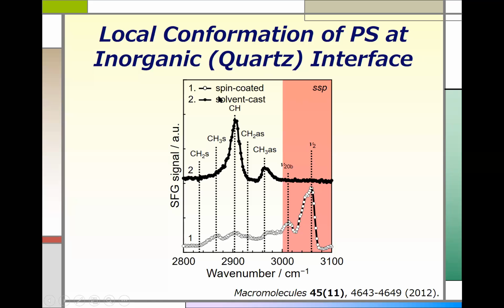So in case of the spin coating method, we have a peak here from 3000 up to 3100 centimeter inverse. Actually, this is the information for phenyl groups. And as I told you, in case of SFG, to get signals, functional groups must be oriented at the interface. So this means that in case of the spin coating method, phenyl groups are aligned, I mean, oriented at such substrate, but that is not the case for the solvent coating method.